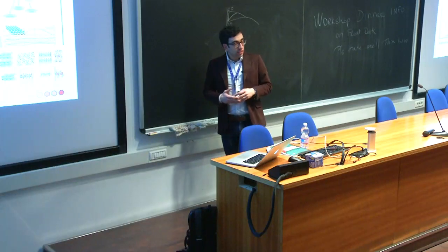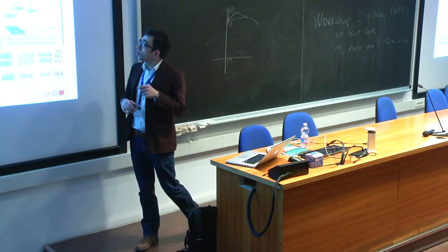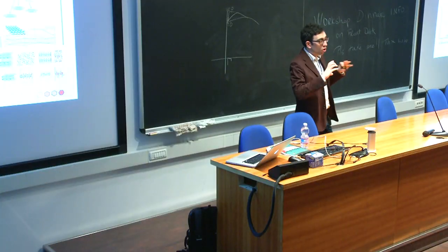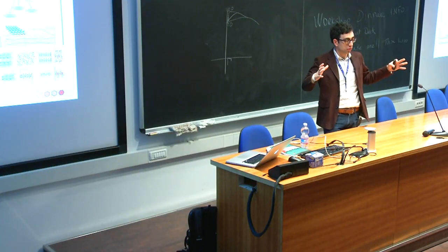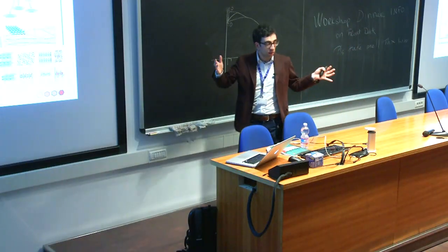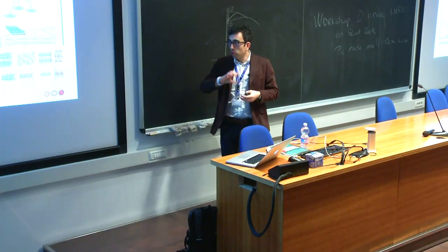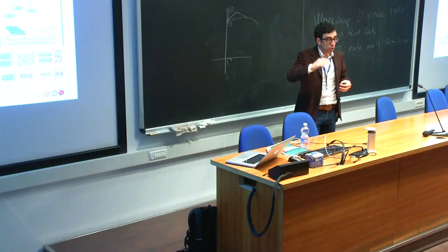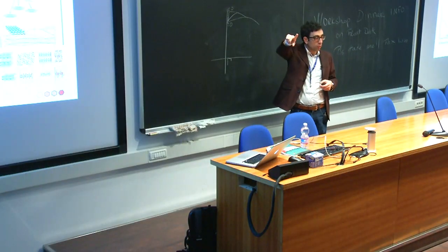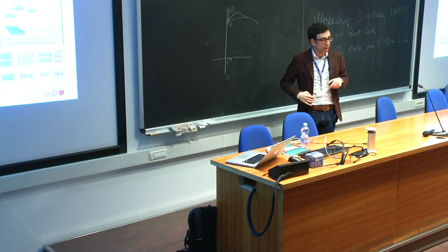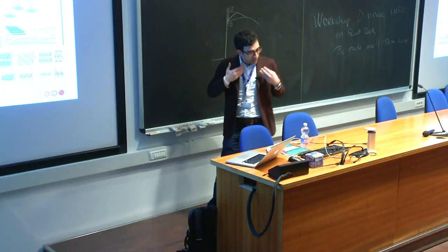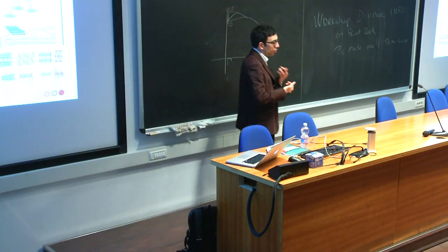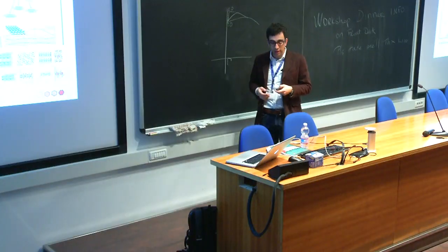And this is being used, for instance, this was one of the modules used in this project, which has been published on the arXiv recently, which was used to, for instance, discover 2D materials in a 3D database. So we started from a three-dimensional database, actually both COD and ICSD. We looked with a geometrical algorithm for layered structures. And these were all tracked with AiiDA. So we really know from which database entry we started, which algorithm, which threshold we used to get the layers, etc. And once we do this, we send this through these workflows to calculate both relaxed structures, but also other properties like phonons, binding energy, etc.